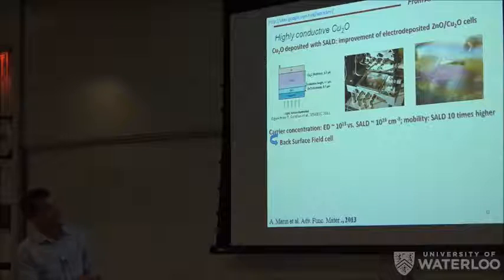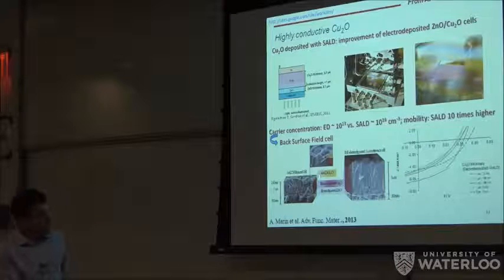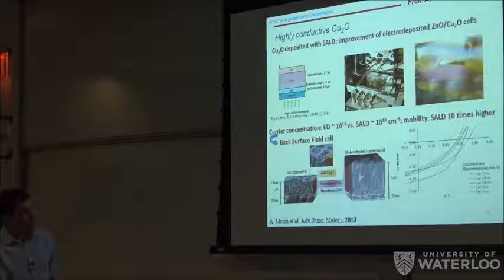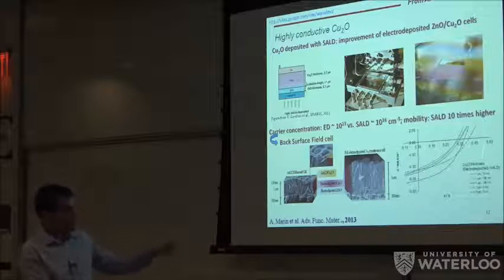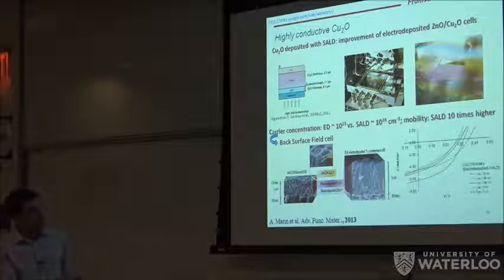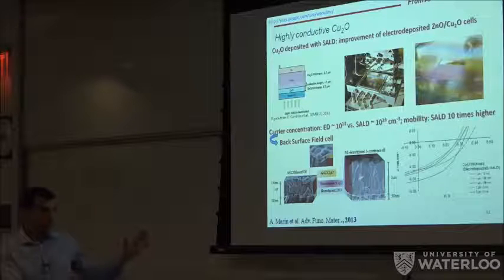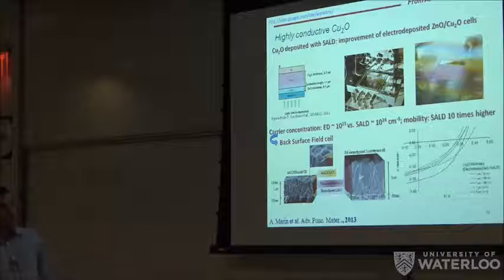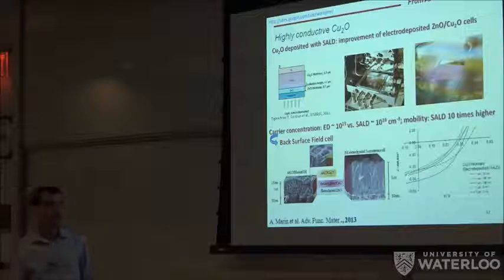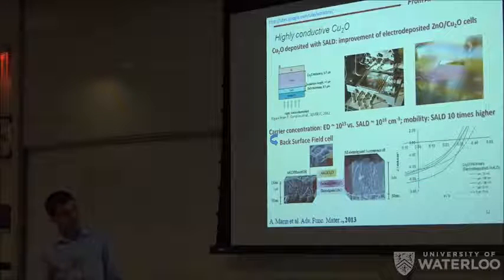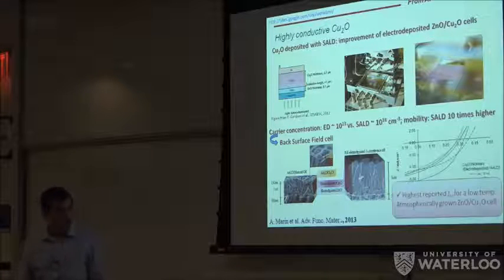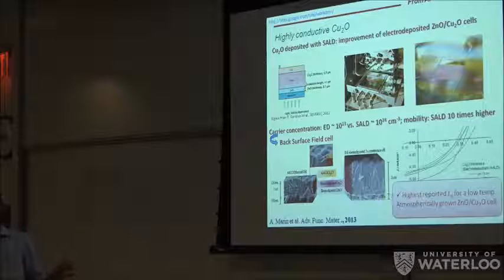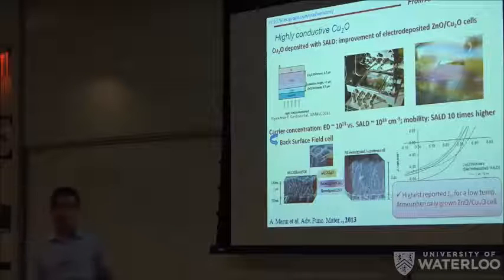And the objective here is to dope some of the holes of the SALD layer into the electrochemically deposited layer. You can see here the cell with the SALD layer. And if you see here the different efficiency for the different cells, you can see that the one in which we deposited this layer of spatial atomic layer deposition cuprous oxide, we managed to increase a great deal the short circuit current. And at the time was the highest reported for this type of system fabricated at ambient atmosphere